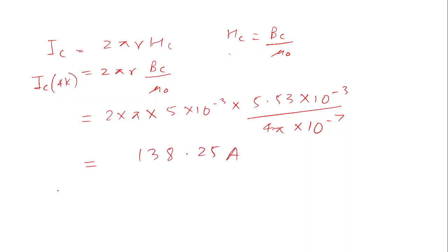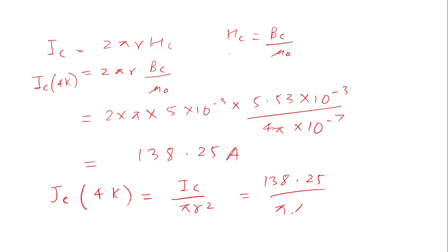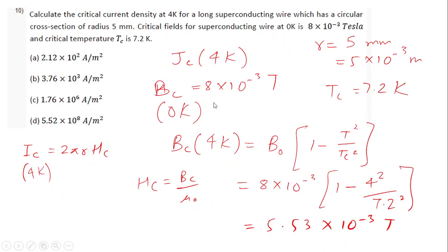138.25 ampere. And I have to calculate critical current density at 4 Kelvin. It will be IC divided by area, pi r square. 138.25 divided by pi times 5 times 10 to the power minus 3, squared. And after calculating this, we will get the answer 1.76 times 10 to the power 6 ampere per meter square, which is the critical current density. So keep these things in mind.